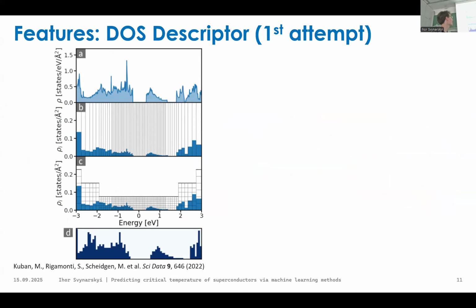So what we are doing with the DOS, we're basically dividing it on this, horizontal, no, on these bars, yes, and then we are calculating, then we're normalizing it somehow and obtaining this descriptor in a similar shape. So it slightly resembles this one, but in a more or less uniform way, because for different compounds we have very different densities. It's an order of magnitude, like 10 times or even more, maybe.